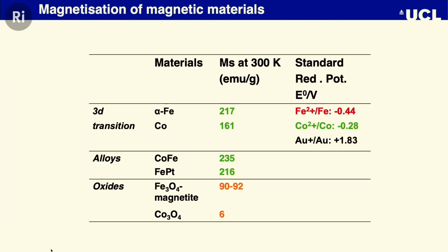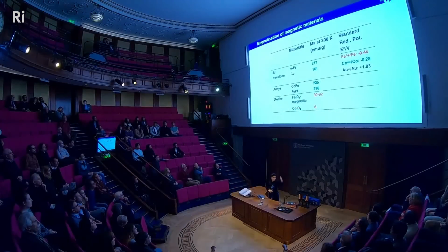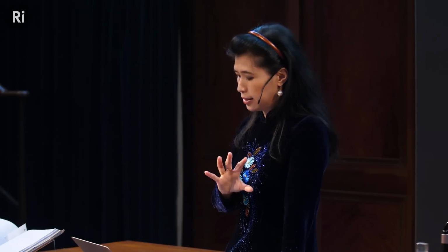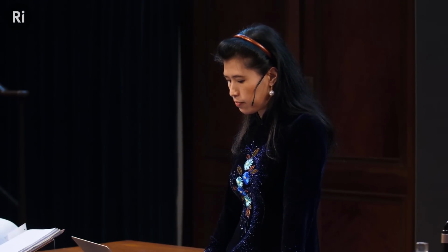We also make cobalt, which has a little less saturation magnetization and is a little easier to work with because it is less prone to oxidation. We also make iron cobalt, and we still try to make iron cobalt now for different applications, and we also try iron platinum. I will come to iron oxide later, but here I just give you an example, I call it this micro iron zero firework.